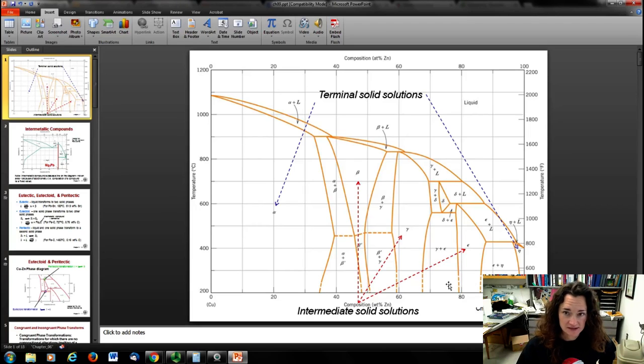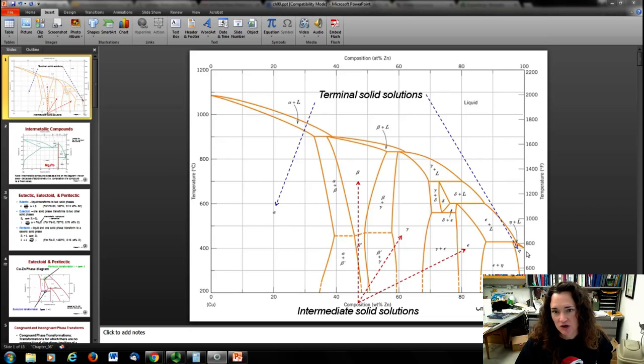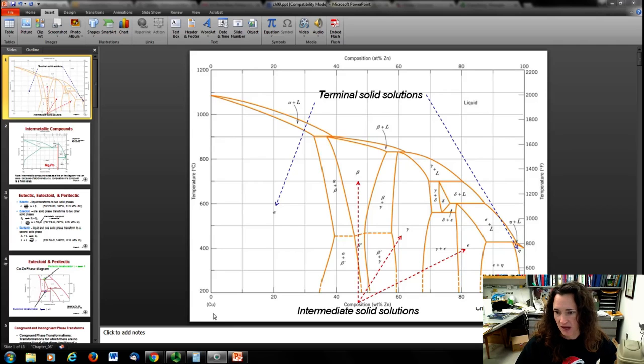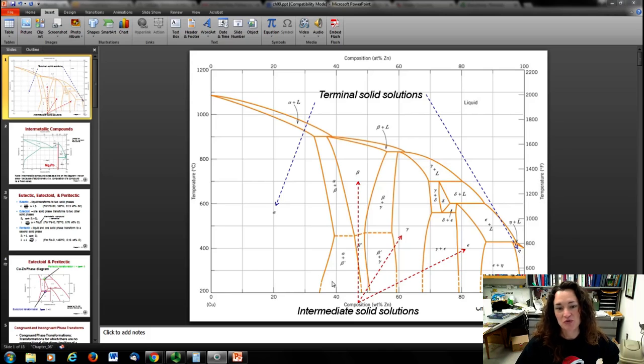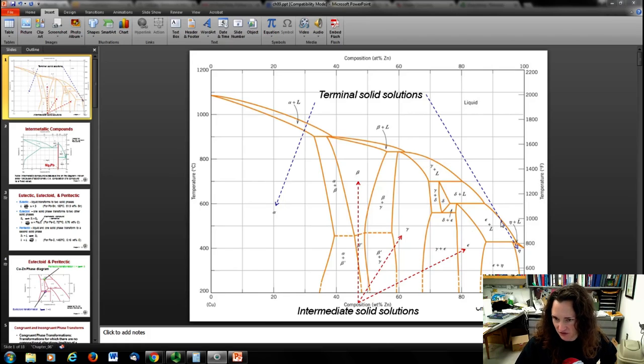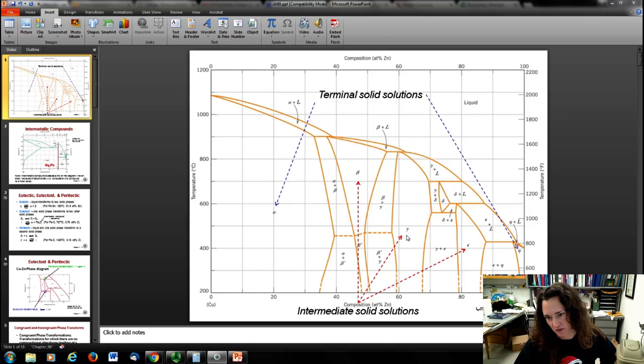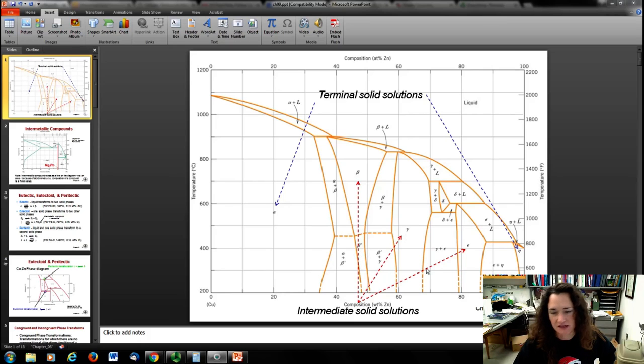Let me go through a few things on this. You've got what are called terminal solid solutions. Along the bottom, you're going from 0% zinc, 100% copper, all the way to 100% zinc on the right. So the alpha phase and the eta phase — yes, that's eta — are the pure copper and pure zinc forms respectively. All along the way you've got different solid phase structures: the beta phase, gamma phase, epsilon phase, beta prime phase, and so on.